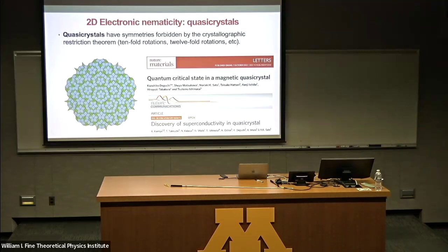So how can we defeat the crystallographic restriction theorem? Well, throw away the crystallographic, right? Quasi-crystals. Quasi-crystals are, I find, one of the most interesting things in condensed matter or, I don't know, crystallography. Crystallography is pretty interesting anyway, but these are systems that have long range orientational order, but no translational symmetry, okay? And the beauty of quasi-crystals is that they are not restricted by the crystallographic restriction theorem. Perhaps the most known case that you probably learned at some point or have seen is the Penrose quasi-crystal.